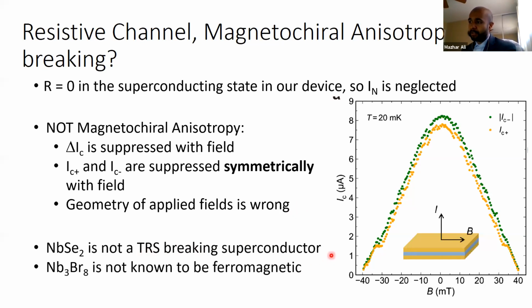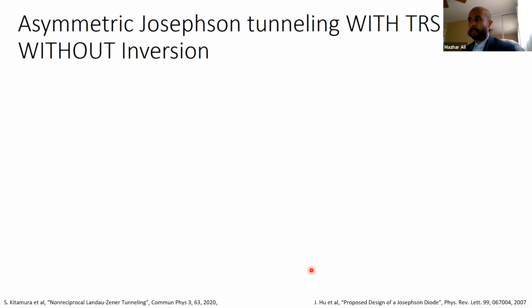Also, just to throw this out there in case there were other arguments about NbSe2 being a time reversal symmetry breaking superconductor on its own, that's just known not to be true, especially not in maybe the thick NbSe2. And Nb3Br8 is not known to be intrinsically time reversal symmetry breaking. Like I said, the work from earlier has pointed to a non-magnetic ground state, and certainly not a ferromagnetic ground state. And while some people predicted maybe in the monolayer these things could be ferromagnets, that's not been shown or seen, and we're thicker than that anyway. So at the moment, there's no signs for this. So basically, we're left with the supercurrent. So, how do you get asymmetric tunneling with time reversal symmetry, but without inversion?